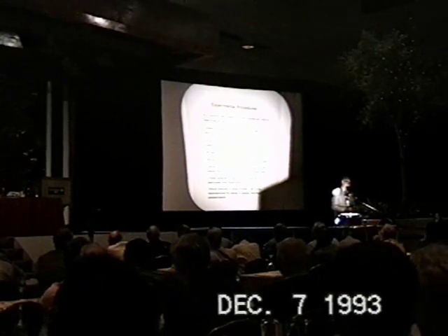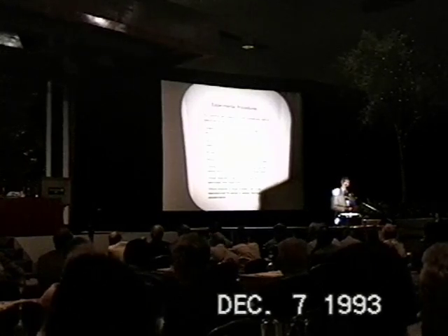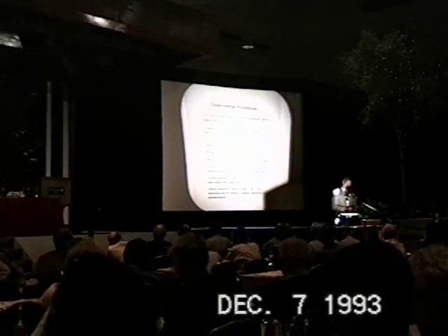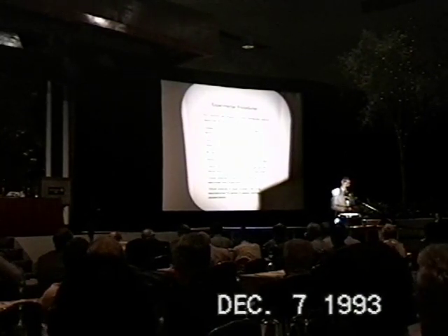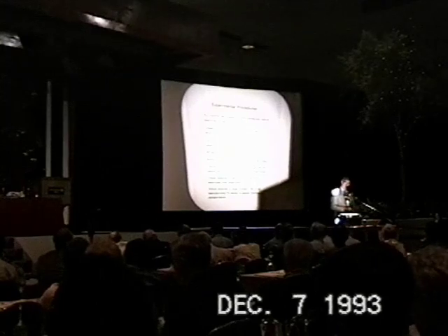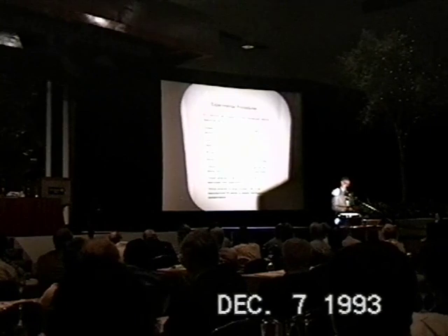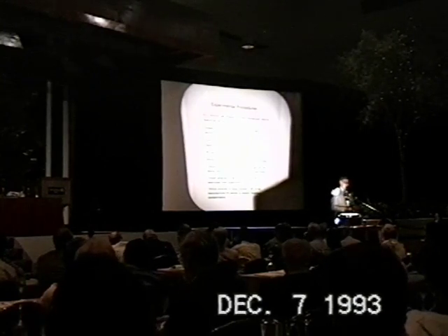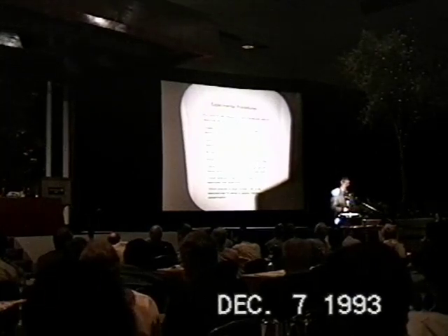We did palladize, meaning we provided the palladium electrodes systematically with a palladium black layer of about 1 micrometer thickness. Let me say quickly that the amount of chemisorption of hydrogen and deuterium in this thin layer of palladium black is absolutely negligible with respect to the amount of deuterium absorbed by the palladium.